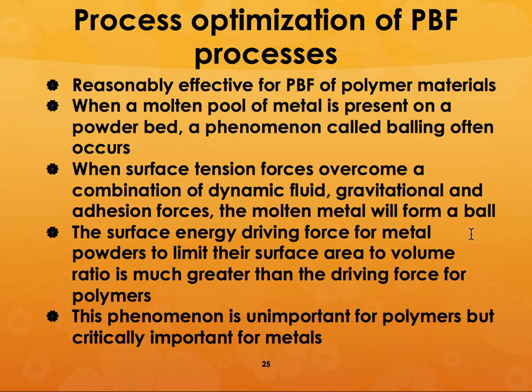Many times what happens is that if you have metal powders, there is a phenomenon called balling. What is balling? Those metal powders can just ball together and form areas where you have some grouping of metal powders, whereas in other areas it is not there at all. And it is a function of the surface tension of the metal pool, the gravitation and adhesion forces. If your surface tension forces go above a combination of dynamic, fluid, gravitational and adhesion forces, then it can form a ball.